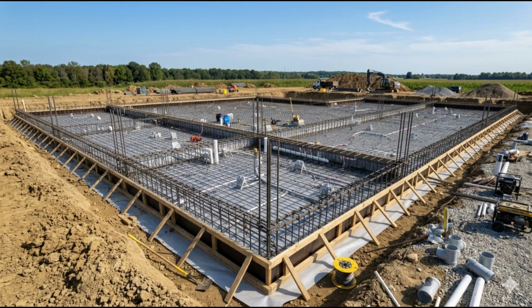He specified that the concrete was to be placed using a long-handled screed or vibrating beam to achieve an accurate surface level, finished with a power float and power trowel to produce a flatness classification of FM2 in accordance with TR34. This being a moderate flatness requirement appropriate for general industrial use, as distinct from the higher FM1 classification required for very narrow aisle, VNA, forklift trucks, which would have required more careful planning and more exacting.